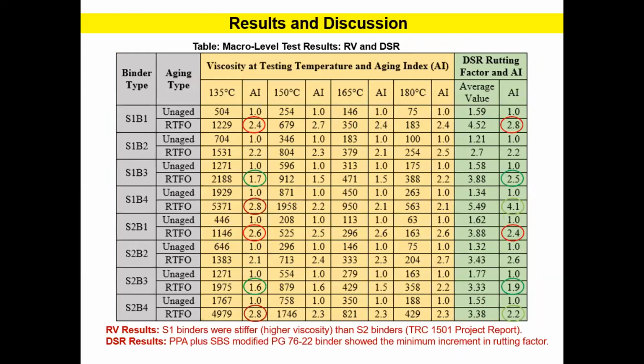Here, the macro level rotational viscometer and dynamic shear rheometer test results are presented along with their aging indices. Based on the RV test results, it has been found that the S1 binder had the higher viscosity. That means the S1 binders were stiffer than their corresponding S2 binders. And these findings are in correspondence with the TRC 1501 project final report. However, the DSR test results found that the PPA plus SBS modified binder showed the minimum increment in rutting factor, while the control binder showed the maximum increment in their rutting factor.